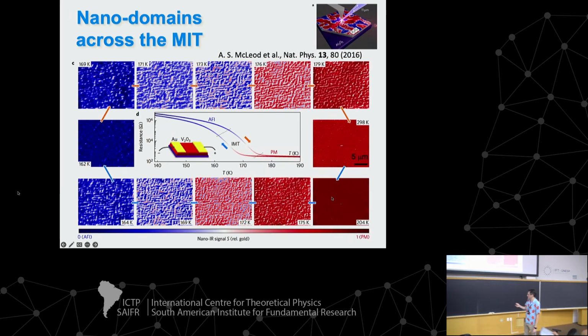Okay. I showed you that there is a hysteresis cycle in the resistivity, and this hysteresis cycle points to the existence of domains, and those domains were beautifully measured by infrared nanospectroscopy. So you can see that in the metallic state, essentially all the sample is metallic, and as you cool down, insulating domains start to show up. Then the full system is insulating, and then as you warm up, you have metallic domains showing up, but there is a clear hysteresis. You see at similar temperatures, the amount of metallic or insulating domains changes depending on whether you are cooling or warming.